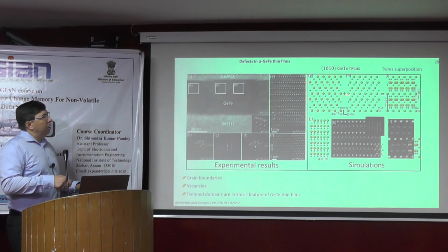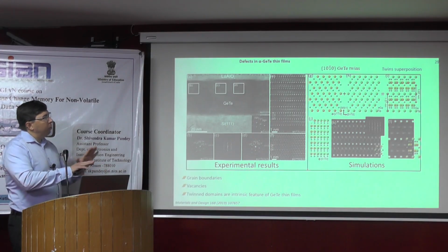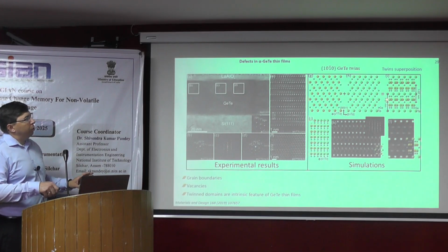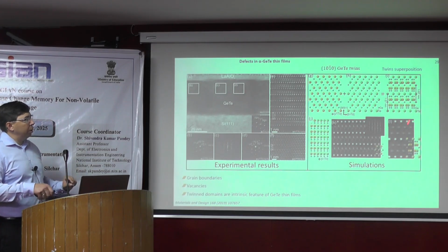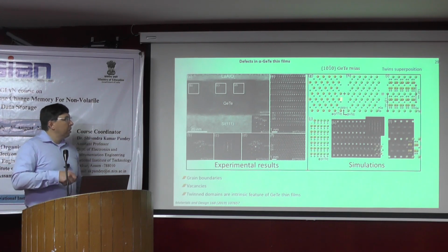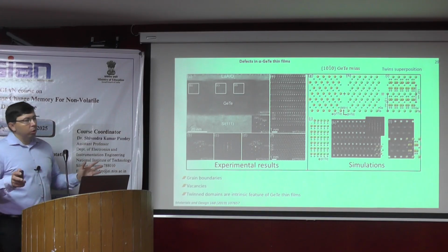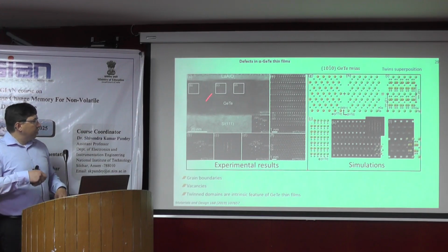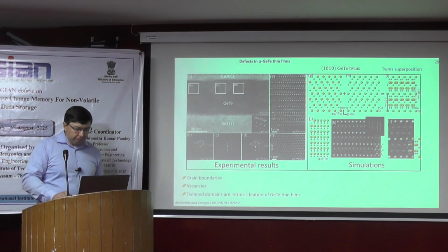But if you allow these two twins to overlap or superimpose, you find positions with distances of 1.7 nanometers. And if you apply simulations, you find that this is actually overlapping domains because of these two twins. So this is not a new structure. If you observe it in your samples, just point to this publication. These are twins which are overlapped one on the other.